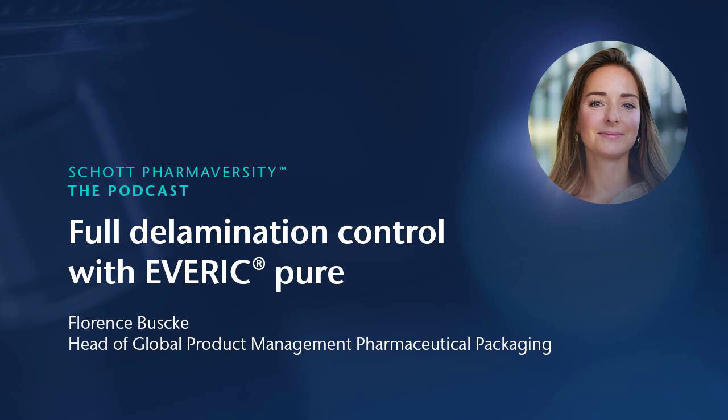As a consequence, the determined hydrolytic resistance is not representative of the concentrations of leached glass elements, as we have discussed before, especially for low filling volumes, which are the real case. And this is attributed to 2 main factors that I just touched on briefly in your question before. First, an increasing ratio of wetted surface to volume, and second, an increased leaching tendency typically observed with borosilicate glass of the wall near the bottom area, as described before, especially when standard manufacturing is applied. Yeah, so the standard manufacturing here is the subject.